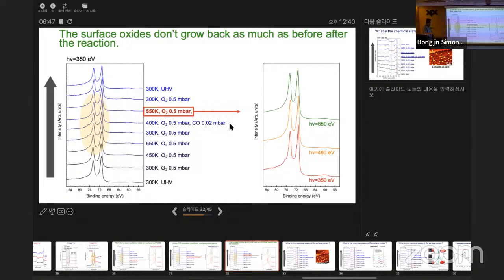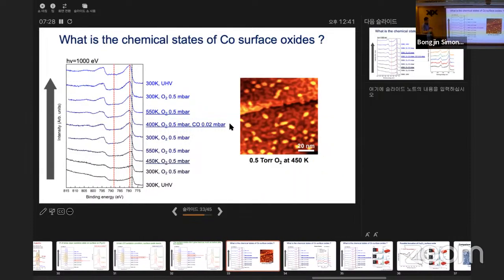Then what we did was we tried whether that oxide that disappeared could regrow if we introduce the oxygen, 0.5 mbar, at 550 K. When you introduce the temperature, would we be able to grow the oxide again? And unfortunately not. The oxide doesn't grow that much. It happened during the oxygen being segregated to the surface: it forms the oxide and reacts with the CO. But once you're done, it's very difficult to regrow the oxide. There's a small amount of oxygen, but it's not a lot. It's not as much as before. So that's what we saw.